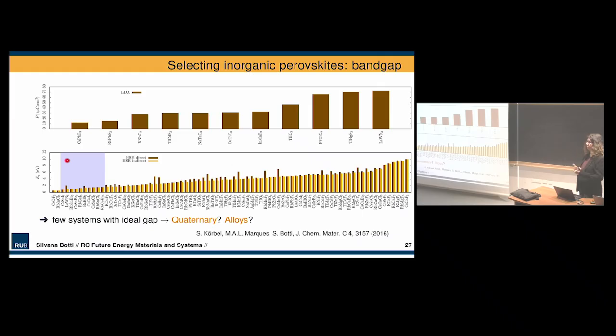Usually when we do calculations with structure prediction, we use functionals that are, let's say, low quality, like the PBE functional that is also used in the Materials Project database. But it's usually enough to calculate energy and forces and build our convex hull, and the calculations are fast enough. But when we look at the band gap, for example, this is not good enough. So for the band gap, we do calculations with hybrid functionals that will give us reliable band gaps in the region of interest for semiconducting materials.